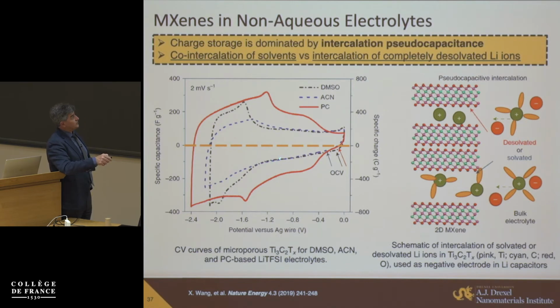But what we found actually is that in the case of acetonitrile, the best electrolyte, we got the worst performance. And PC, with an order of magnitude lower bulk mobility and ionic conductivity, gave us a much larger area under the curve here, much larger capacitance.